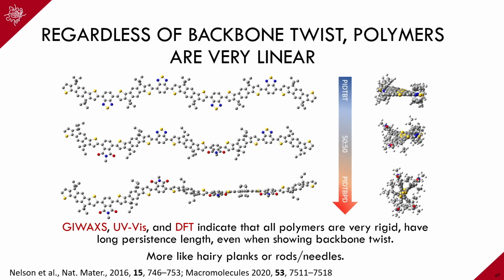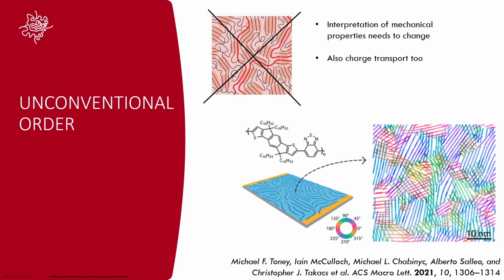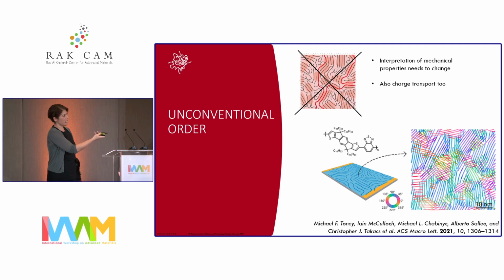So through all our failures and through all our characterization, a different picture was emerging, that these polymers were not the spaghetti that we draw, but really more rigid planks. And our collaborator, Alberto Salleo, actually confirmed this using a different TEM technique as well, which is that the way that we draw these polymers is really just simply wrong. And the way that you should envision them is these needle-like structures or plank-like structures.